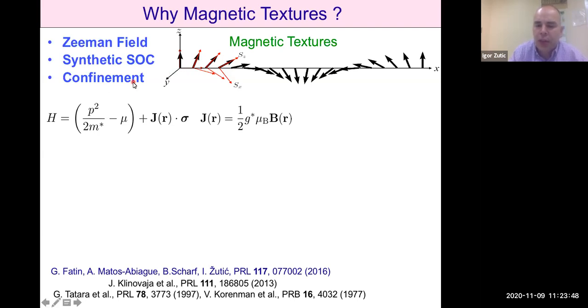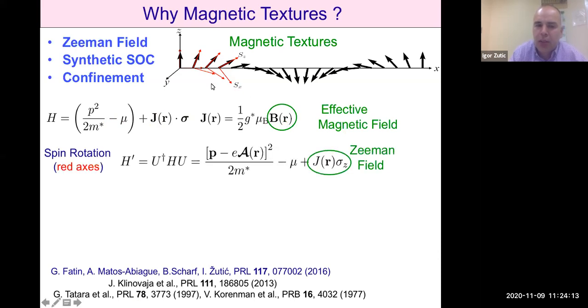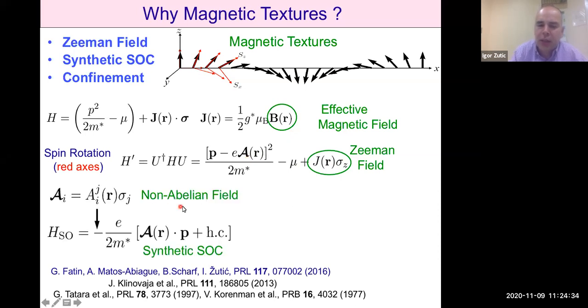When we do that, which is a standard trick in spintronics and other fields, so you can see references from many years ago, we can transform this simple Hamiltonian where in addition to the kinetic term, we have some magnetic exchange. This magnetic exchange gives us an effective magnetic field, and we may be able to simplify it by this rotation of the spin axis. So we may just diagonalize it, and this magnetic term now becomes simple. But as we make this magnetic term simple, we make the kinetic term more complicated. And what we have as a result of this complication is effectively a non-abelian field, or if you wish, synthetic spin orbit coupling.